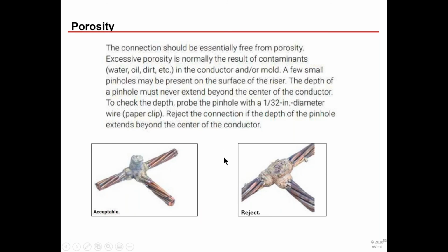Here's one called porosity. These are pinholes that happen within your weld. You might have some, but you can see the examples here. Here, this is completely covered, as smooth as the picture, and you don't see a bunch of pinholes. Here, it's all over the place. That means there were contaminants within the mold. You can have pinholes, but like it says here, basically take a paper clip and put it into the pinhole. If the depth of the pinhole extends beyond the center of the conductor, you need to replace it. That means you do not have a quality weld there. You have gaps.